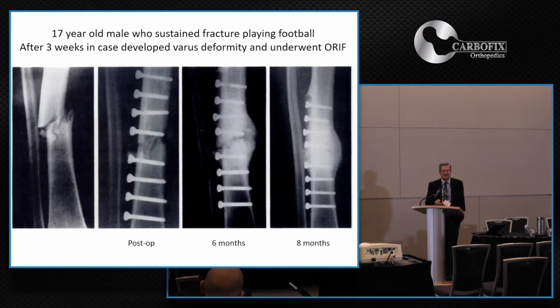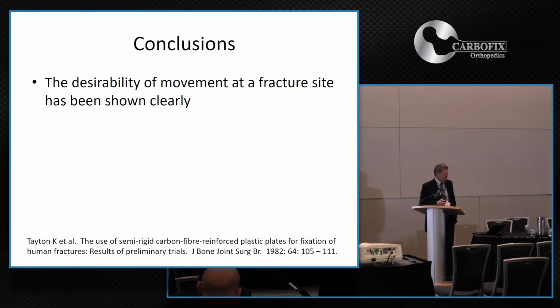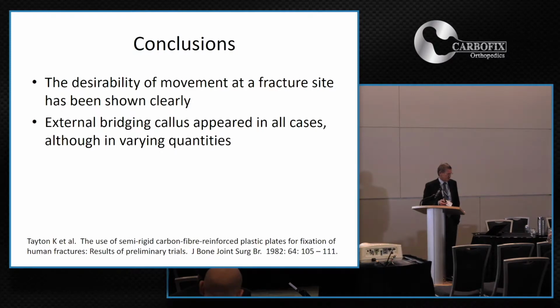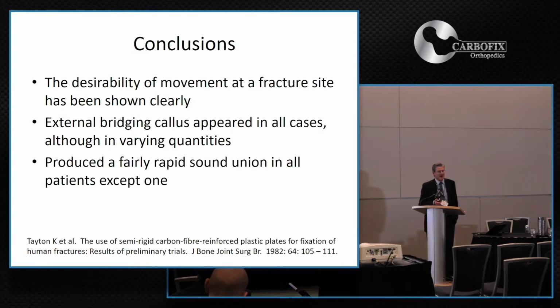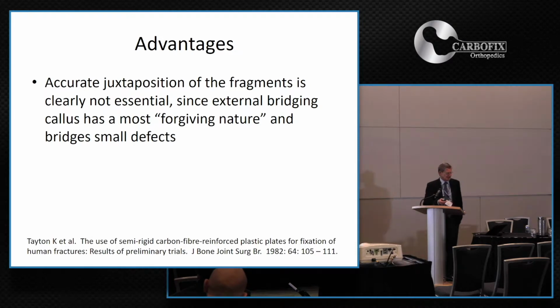And here is an example showing one of these clinical cases that's in the literature, showing the abundant callus at the fracture site. And they concluded that the desirability of motion at the fracture site was clearly shown, that external bridging callus appeared in all of the cases, but in varying quantities, and it produced a fairly rapidly sound union. And they went on to say that the accurate juxtaposition of the fragments is clearly not essential, since external bridging callus has a most forgiving nature in bridging small defects.